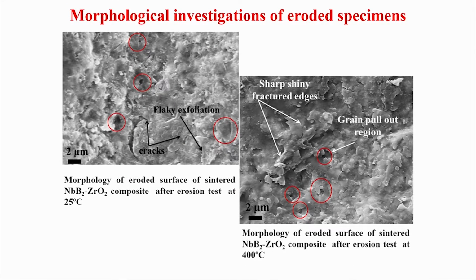Now, as I said, as a material scientist who has great interest in tribology, we are always interested to see how these wear mechanisms change at different temperatures. So, this one is at 25 degree room temperature, and this one is at 400 degree Celsius. At room temperature you can see signatures of flaky exfoliation, as well as small cracks, which you can see very easily. These cracks are present, but at 400 degree Celsius, after the erosion test is over, you can see signatures of pull out. This is the circle the way I am tracing, the circle for the grain pull out region, and sharp and shiny fracture edges are also clearly observed after testing at 400 degree Celsius.